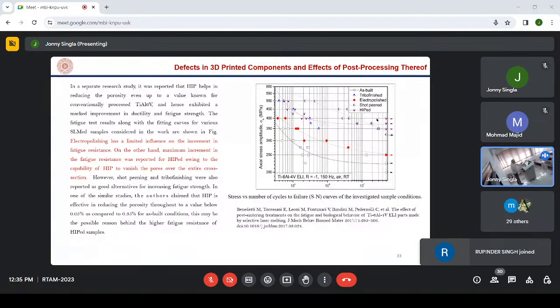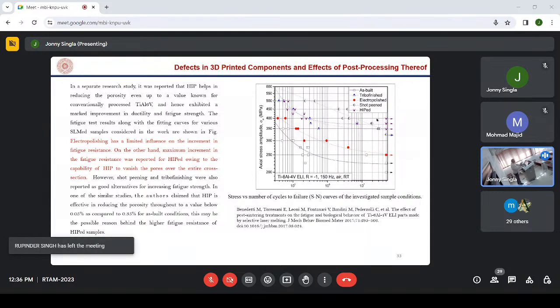Similarly, this is compared with other treatments: shot peened, electropolished, tribo-finished, as-built and HIP. All these have been compared, and it has been found that shot peening and HIP improve high cycle fatigue strength, and for very high cycle fatigue strength, that means more than 10⁸ cycles, HIP is the most desirable, right?